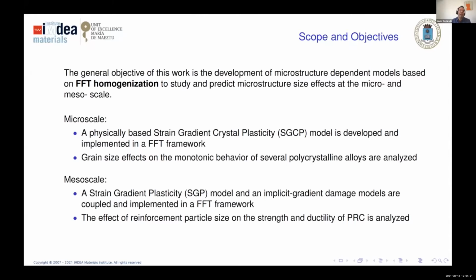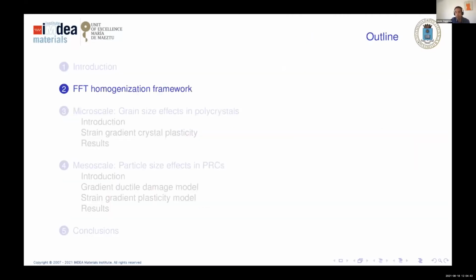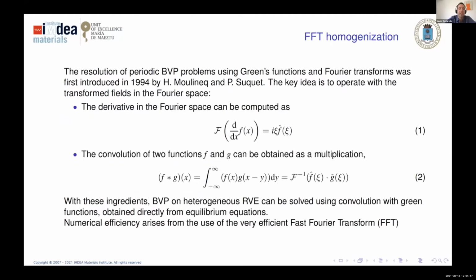Okay, and in this case, we will present two works. One is on the microscale, where we will study, through a strain gradient crystal plasticity model, the grain size effect, and another one is on the mesoscale, where combining strain gradient plasticity with an implicit gradient damage approach, we will study the effect of particle size in particle reinforced composites. Okay, which is the common homogenization framework?